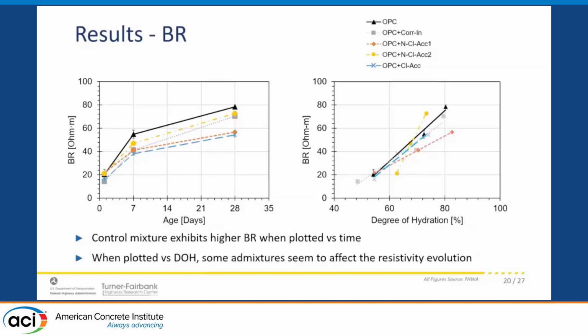And it's not necessarily reducing the resistivity. Once we correct for the degree of hydration, so we're not thinking about days anymore, but looking at the bound water or the total enthalpy of the system, we can see that the curves pretty much collapse. So we are altering the degree of hydration evolution over time, but once we account for that, there's not so much difference between the different systems.